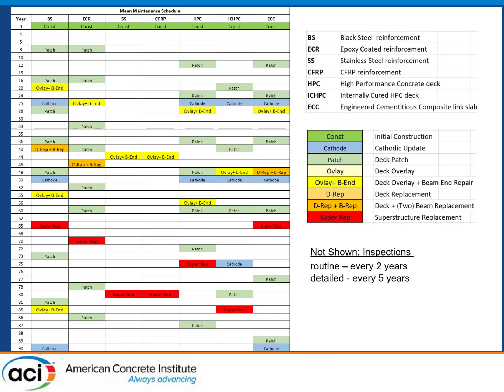And this schedule shows, first on the very left, the Michigan baseline for unprotected steel and normal concrete. Then the next would be epoxy coated bars, ECR, stainless steel, CFRP bars, the HPC mix that we had data for, the internally cured HPC mix, and then the engineered cementitious composite link slab.